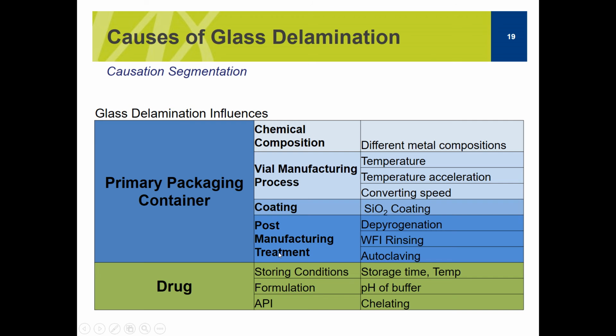Again, this is a similar graph, a similar table, and it really talks about the influencers of glass delamination. It starts with the glass chemical composition, the vial manufacturing processes, the coating, if we are putting on a coating such as SiO2 coating or siliconization, and then also post-manufacture treatment: depyrogenation, WFI rinsing, and autoclaving. All of these influence the formation of lamellae, or glass that delaminates. And in green, this is going to be a separate module itself. It talks about the drug and container interaction and how the different characteristics of the drug increase the risk of delamination.